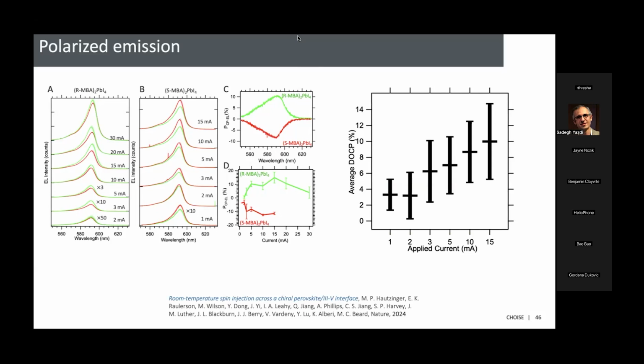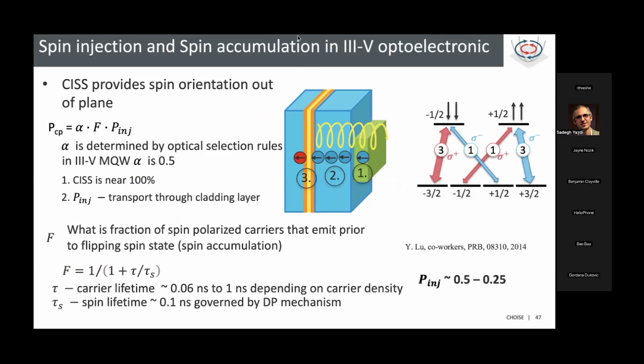And so you can get a degree of polarization of over 15%. So that's good. It's already improved the spin polarization out of this device from 3% up to 15%. All right, so of course, what we're showing here, and what's important for this kind of thing, is that we can get spin injection across this chiral semiconductor interface, and we get spin accumulation in the emitter layer that's not chiral. Okay, so that's what we're getting at room temperature with no ferromagnetic components.